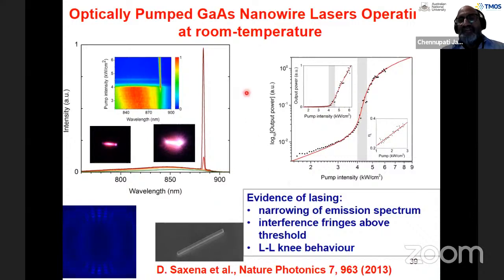This really created a lot of excitement in the community, the ability to make these gallium arsenide nanowire lasers, because the surface recombination velocity of gallium arsenide is very high. So that's where we really need to do some surface passivation and all sorts of things, and also get high quality nanowires in order to make these nanowire lasers. By the way, just to give you an idea of the dimensions of these lasers, typically I can put about 10 to 20 lasers within the width of your hair. That tells you how tiny these lasers are.